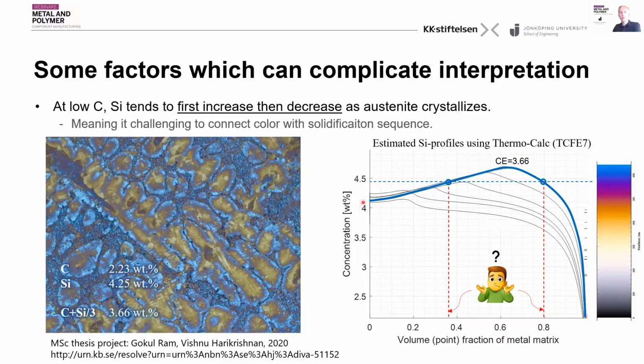We made a calculation using data from a Thermo-Calc database in order to estimate what the expected segregation would be. And then we actually see on these curves for this alloy that the concentration of silicon in the metal matrix increases until about 60% of the material is solid, and then it starts to decrease again. And in these special cases, it might be a bit more difficult to interpret the structure, because a single color can refer to different parts of the solidification sequence.